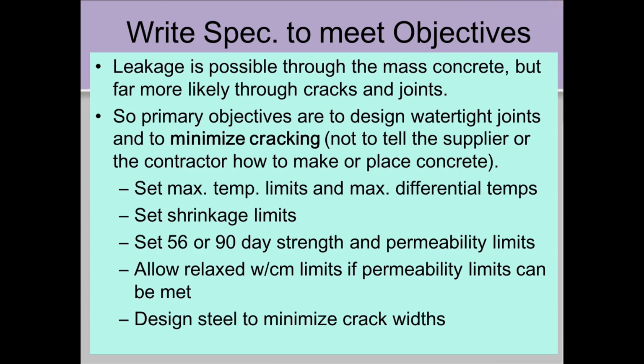So it is possible that you're going to get leakage through the mass concrete, but it's far more likely you're going to get leakage through the cracks and joints. The primary objective is to minimize cracking. So in terms of a specification, we need to set temperature limits and differentials, set shrinkage limits, allow permeability and strength limits to be extended out to later ages, 90 days if possible, and use permeability-related performance specs rather than water-cement ratio if it helps reduce the cement contents. We minimize the thermal gradient, and we want to design it to minimize crack widths.